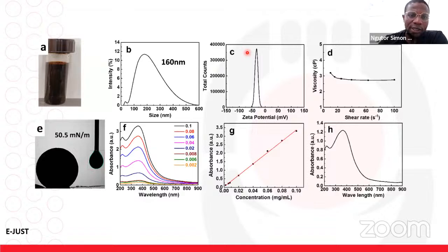So we have had electrochemical characterization. We have done the zeta potential to know the stability of the ink we made. The higher it is away from zero, whether negative or positive, the better, and we had a good stability of the ink and the size of the material. And then we had the UV calibration. As you can see, the absorbance of the material increases, and the concentration was in a linear range, showing the stability of the material in the solvent.